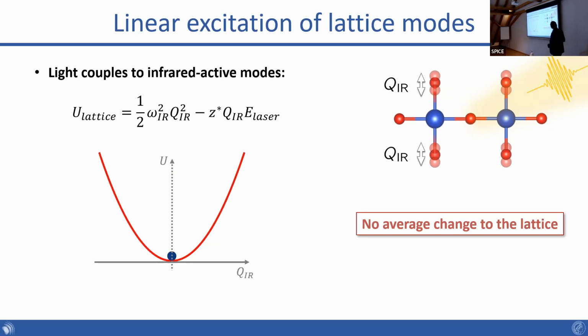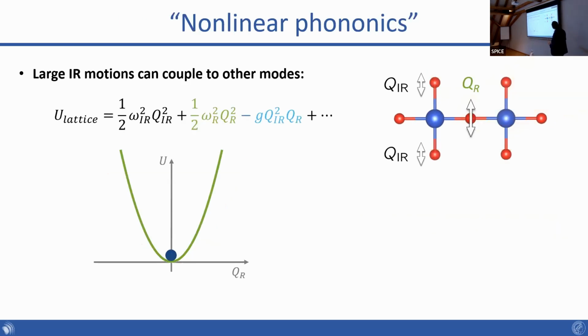And essentially, when you increase the strength of your electric field pulse and drive the modes to larger amplitude, you can get additional terms that will help you. And one of the things that will help you is that you can now couple different modes together, as Andre mentioned. And so now let's take a look at what happens if we have not one, but two modes. Again, a little toy system. One is the original one that we were talking about, and another one is this mode that I'm calling QR, which is a Raman active mode, which wouldn't normally couple to the electric field. And let's say it corresponds to this motion of this atom up and down here.